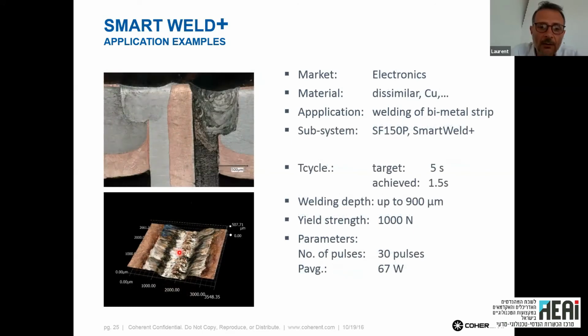Because I have a very, very small spot size, 30 micron, I'm also able to really manage the power on my melting pool, specifically when I have dissimilar materials. In this case, we have copper on one side, and on the other side, it's aluminum. And because I'm moving from one side to the other, I'm able to be very, very accurate. I'm able to spend maybe more time on one material and not on the other in order to create a correct melting pool and to not create any porosity or cracks.